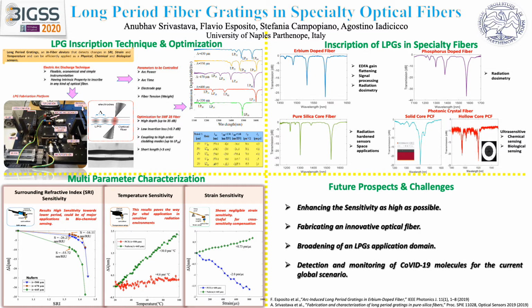You can see also here the inscription of LPGs in different kinds of specialty fibers, like erbium doped fiber, which is used for gain flattening in signal processing and as radiation dosimetry. We achieved a very good transmission spectrum approaching around 30 decibel. Likewise, in phosphorus doped fiber, which can be used as radiation dosimetry, we achieved a very good spectrum approaching around 35 to 38 decibel.